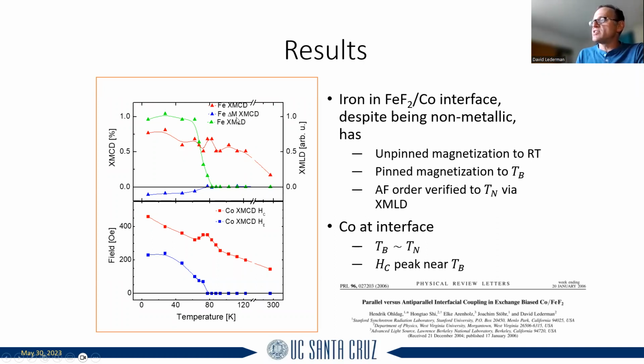And then you have the circular dichroism of the iron, and you can see that this persists up to room temperature. And then in addition to that, you have this thing which is the shift, right? Those are those pinned moments, and you can see the pinned moments actually disappear at the same point at which the iron fluoride orders, right? And this is kind of like a measure of the exchange bias.